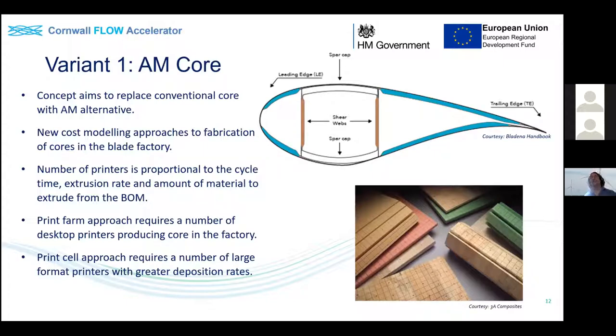So you can see in the top right figure, foam, or not necessarily foam, but usually it's a cellular foam plastic, is used to stiffen the composite skins between the leading edge at the front here, which is marked, the structural spar cap in the middle, and between the end of the structural spar cap and the trailing edge. So these panels are actually placed to increase the localized stiffening response of the blade, so you don't get buckling failures. And the tricky part, obviously, is to size those, both the strength and the thickness of these foam cores, to make the minimum possible mass addition to a blade while maintaining those loads.